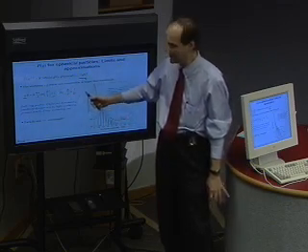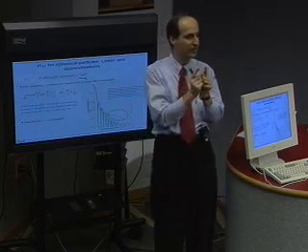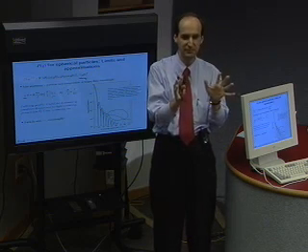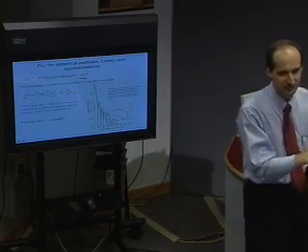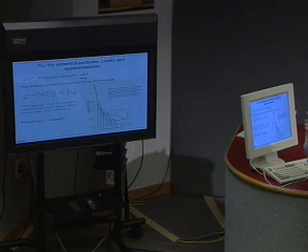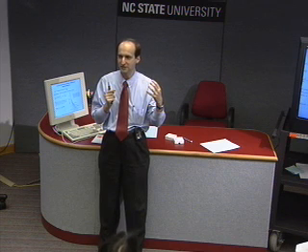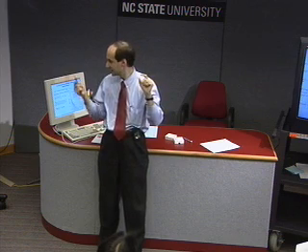So this means that you can take a suspension of particles. If you have this type of scattering, you can very well fit their radius and find their shape. There are formulas for all types of particles which have been developed theoretically: ellipsoidal, needle-like, and so on, what type of scattering function you're going to get. You can take the scattering pattern, fit it, and obtain the particle size. This is also routinely done for emulsions, to measure emulsion size, for example, because emulsion particles are micrometer in size and they are exactly in this scattering regime.